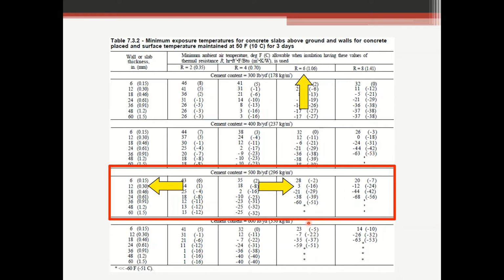So let's say we're placing concrete and we anticipate the ambient air temperature to get down to 3 degrees, so single digits, 3 degrees during our 3-day protection period. We've got a 12-inch foundation wall. Again, our mix has a minimum 500 pounds per cubic yard of cement. Our temperature is going to get down to 3 degrees. This R value of 6, if we protect it, in theory, we should be able to keep that 50-degree Fahrenheit for 3 days. So that's how this table is used. Very, very useful in the field for inspectors, contractors, engineers visiting a job site during cold weather. This is a great table.